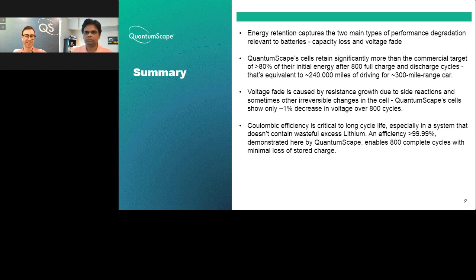We talked about discharge energy rather than capacity because discharge energy is what matters to a driver. You need energy to drive a car, not just capacity, not just electrons. We talked a little bit about voltage fade, and you saw that voltage fade is caused by either a change in the cathode active material or resistance growth, and that all of those mechanisms combined showed only about a 1% decrease in the voltage over 800 cycles. And then we showed the hysteresis. We also showed coulombic efficiency of the batteries. So we talked about energy efficiency, which was roughly 95% under these conditions, and then coulombic efficiency, which was over 99.99%. So very few of the atoms are lost.